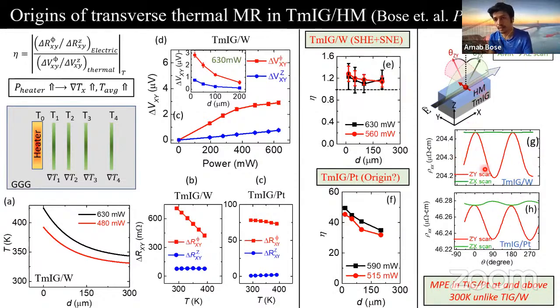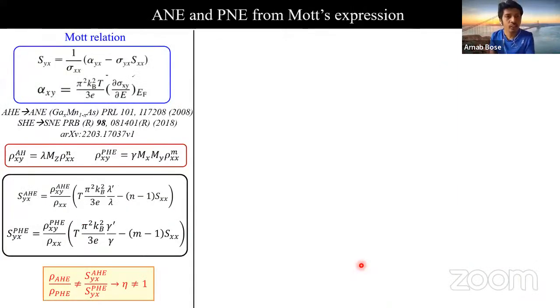In the YZ scan, we find large oscillation in magnetoresistance for both cases, meaning we have very strong spin Hall effect generated by both tungsten and platinum. But for the TMIG platinum sample, we do observe the oscillation in magnetoresistance in the XZ field scan as well, meaning we have a bit of conducting magnet at the interface, unlike the case of TMIG tungsten. So we refer to this proximitized magnet at the interface as the source of this substantial deviation of eta, which makes it different from 1. This is also consistent with the Mott relation. It suggests that we can quantify the transverse thermopower if we know the longitudinal and the transverse resistivities.